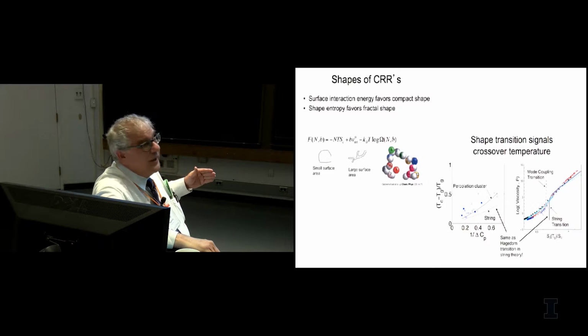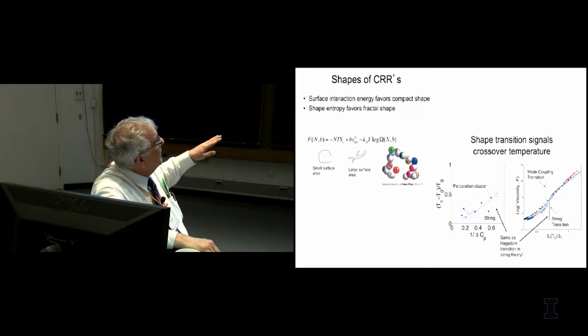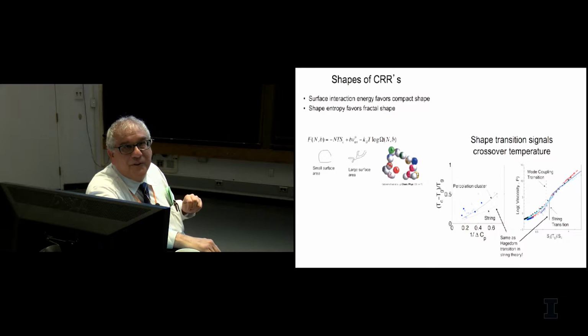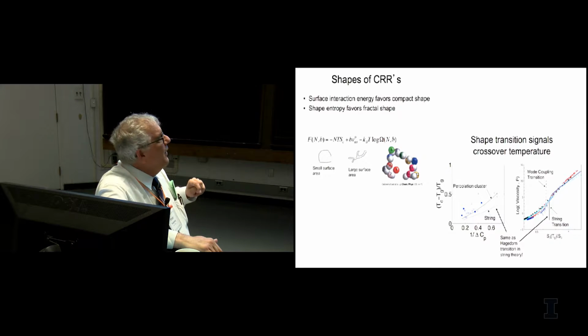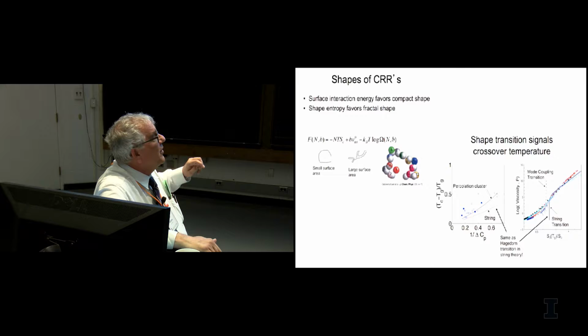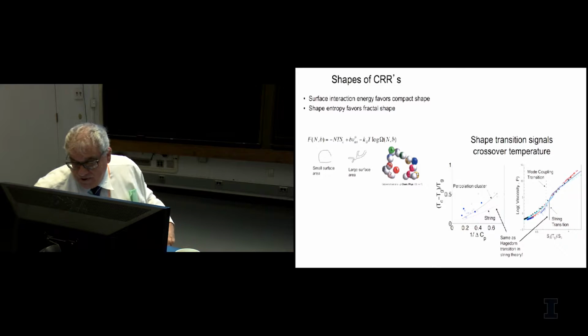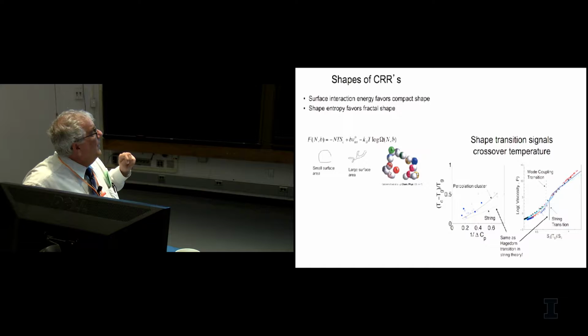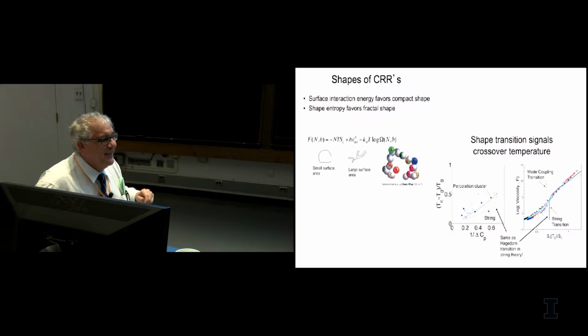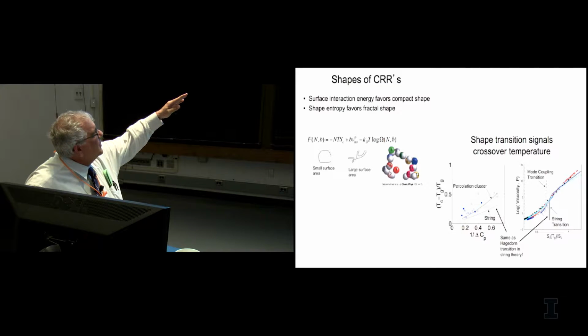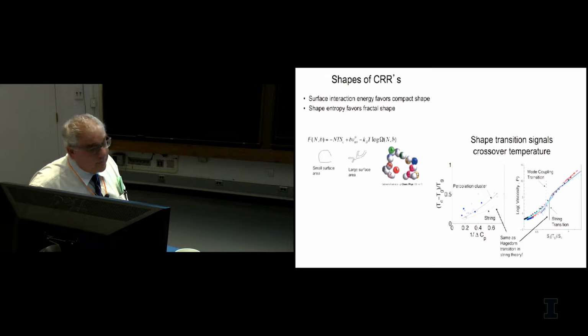So this allows you to predict the temperature at which you start to get the non-Arrhenius temperature dependence, this crossover temperature. And the theory of this is actually very similar to the theory of what's called the Hagedorn transition in string theory. And at least before the last few years where this AdS stuff came in, I said, well, this shows that string theory is a theory of something, but perhaps not a theory of everything. So actually, this is a comparison of the experimental TC minus TG versus 1 over delta CP. It's predicted to be a slightly curved line.